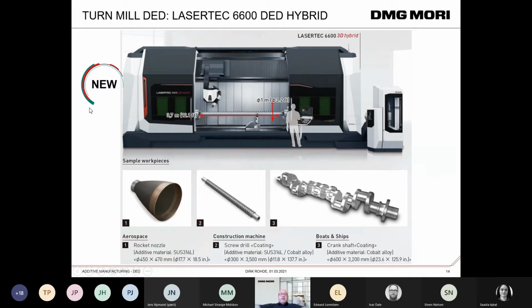We also have, and that's brand new, a first installation running these days in the United States. That's a turn mill center, up to 6 meters in between the spindles, with a maximum diameter of 1070 millimeters. You see the ratio between the operator shown on the panel and the machine size. This is really, really big. And right now we see the focus on coatings, on shafts, every kind of shafts and crankshafts and whatever is long and requires a coverage.